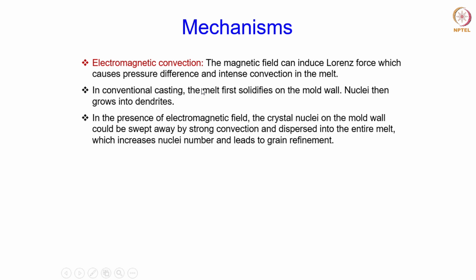And then we finally talked about electromagnetic convection. This is where the electromagnetic field is utilized. The force that is induced due to this electromagnetic field is known as the Lorentz force. This is what leads to the sweeping away of the mold wall crystals and dispersing them into the liquid metal, leading to more nuclei and hence a higher nucleation rate, which will provide grain refinement. Okay, so these are the things that we discussed in the previous class.